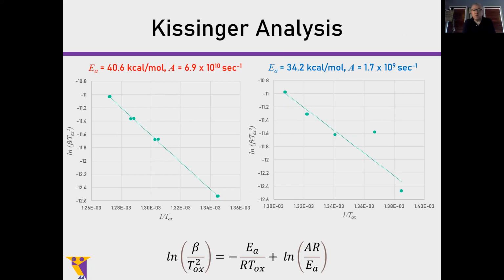Well, prove it. You can get two curves. Well, there's something called Kissinger analysis. What Kissinger analysis allows you to do is to take the peak of the activation, or the peak of the derivative curve, and to plot it against the heating rate. And when I did that for the peak in blue and the peak in red here, you'll notice that I got two very straight lines. Now, this isn't confirmation, but it's certainly not dismissive. There might be something here. They might literally be two different chemical species in the material.